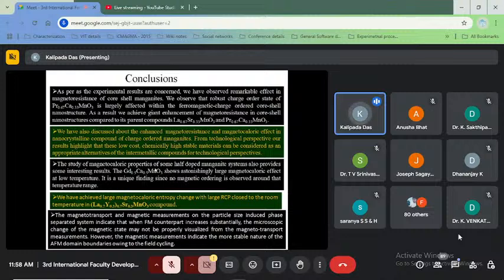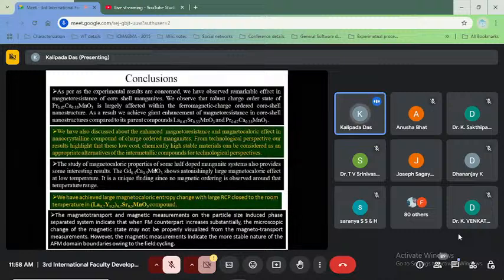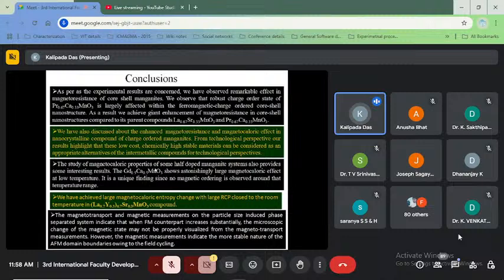Now I conclude my talk. As far as the experimental results are concerned, we have observed a remarkable effect in the magnetoresistance in core-shell type nanostructure, where the magnetoresistance and magnetocaloric effect both get enhanced. And this enhancement is basically due to the change of the magnetic configuration of its magnetic ground state.